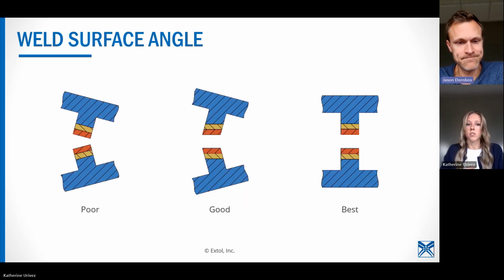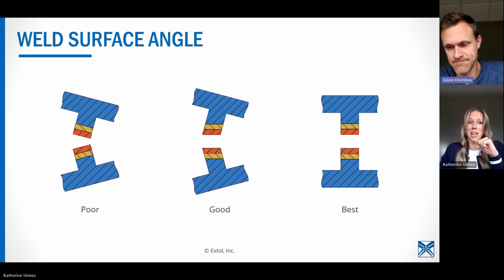Weld surface angles. Similar to that weld contour of 30 degrees, you want your weld surfaces to be parallel to each other because of that force of sealing, the direction that the force is sealing in. So we do not like to see this condition. What happens is you'll displace all the material on this right side. So you're touching cold material and cold material, which is bad. And then you'll maybe just barely have some soft material touching on the left side here, which is also bad. So it does not produce a strong weld, is not recommended.